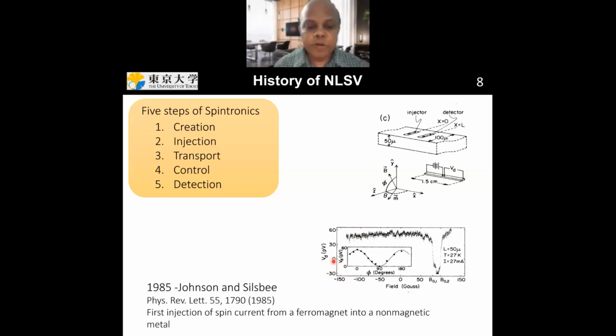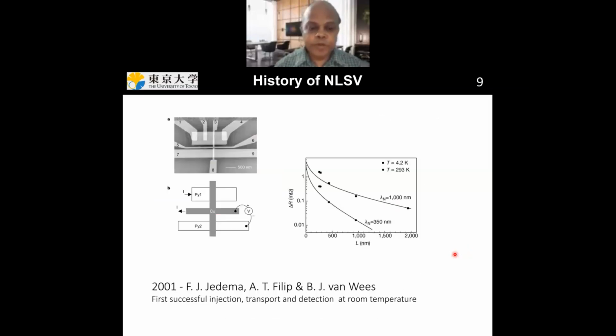But people were not much interested in this because this measurement was done at a very low temperature, 27 Kelvin. The first room temperature non-local spin valve device was made in the year 2001 in the Bart van Wees group in the Netherlands. They could measure non-local experiments using a copper spin transport channel at room temperature, and they found the spin diffusion length in copper is around 350 nanometers. After this, people were much more interested in this kind of devices.